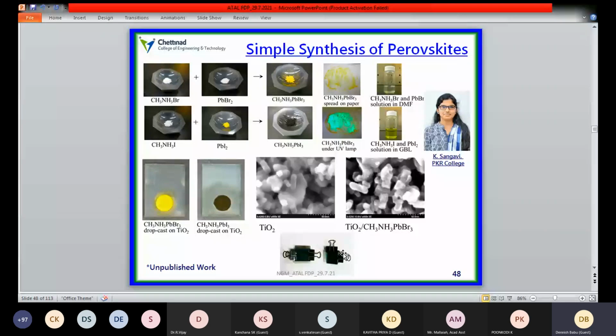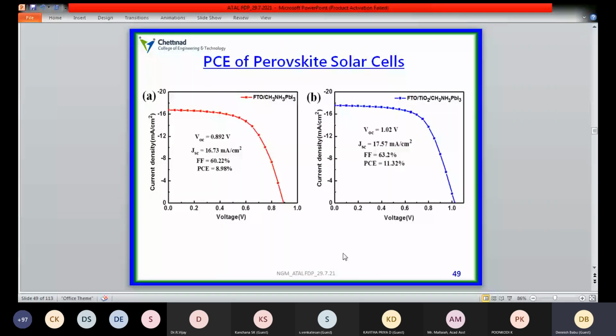And this is the first power conversion efficiency result when we use traditional titanium dioxide based perovskite without mesoporous material. It is exhibiting 8.98% power conversion efficiency. And if we include mesoporous titanium dioxide onto that, it will easily increase the power conversion efficiency from 8 to 11.32%. So this is the initial research work that we have made on perovskite systems.